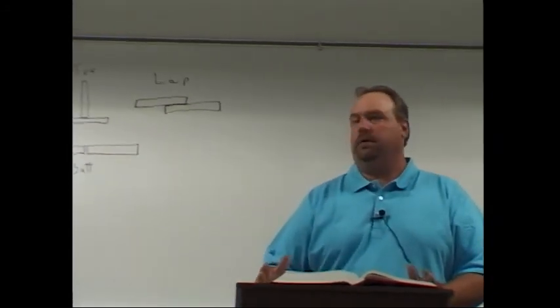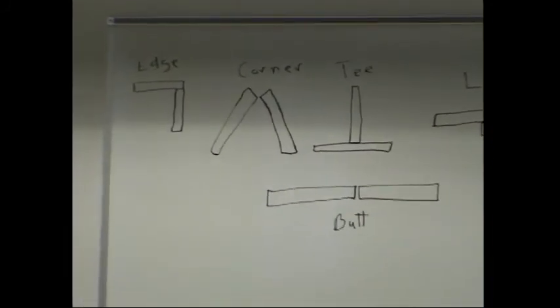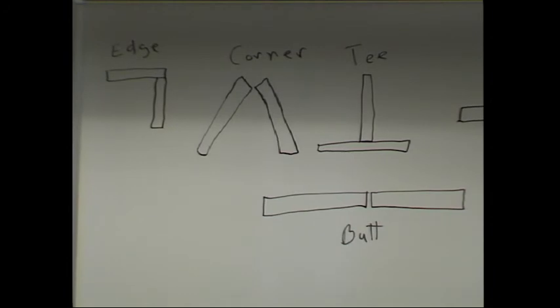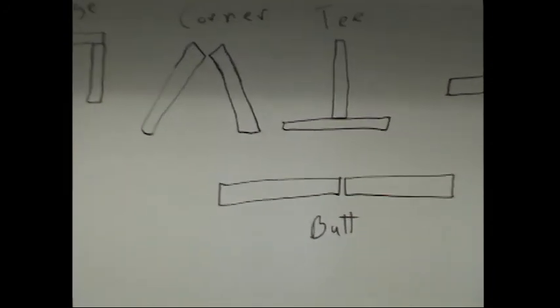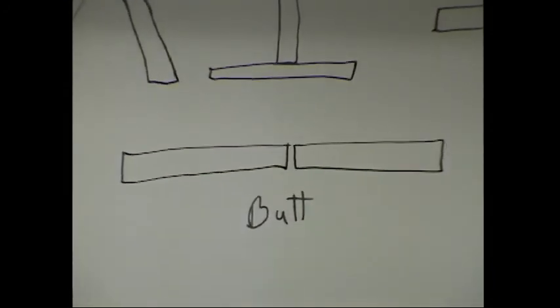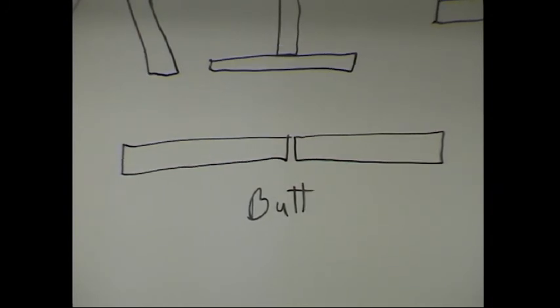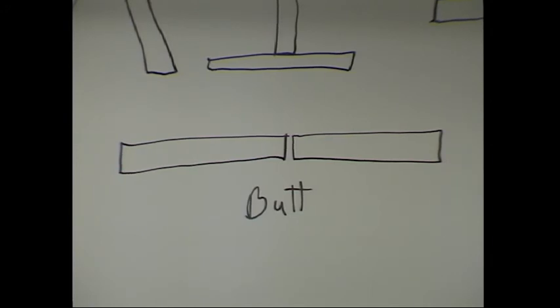Square butt joints, like I said, on sheet metal, when you're doing stuff that's an eighth of an inch or less thick, you can just go with a square butt joint, like you see on the bottom down there. It doesn't require any beveling or any preparation to that joint whatsoever. You'll just have to leave a little bit of a gap to give you room to push your filler metal through for a full penetration weld.